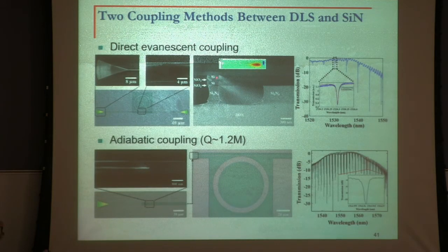Some examples of the devices fabricated, again, silicon nitride. Coupling is done using tapered couplers. Signal goes into this structure, and that is, again, the response, very good tapered coupling. And the quality factors are also in the million range, 1.2 million for this example. So it's not an easy material to develop, but thanks to extensive development and IEN facilities, we were able to get into this place. Now, this is a recent result, unpublished yet. So that's what we are working on now to demonstrate a material in this platform.